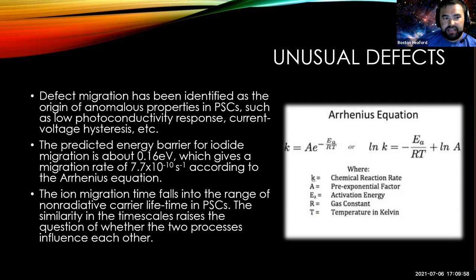in the perovskites with defects, the defect migration has been identified as the origin of some anomalous properties of perovskite solar cells, such as low photoconductivity response, current-voltage hysteresis, and a few others. And the predicted energy barrier for iodide migration is about 0.16 electron volts, which gives a migration rate of 7.7 times 10 to the negative 10 per second, according to the Arrhenius equation. And the ion migration time falls into the range of non-radiative carrier lifetimes in perovskite solar cells. And the similarity in the time scales raises the question of whether the two processes influence each other.